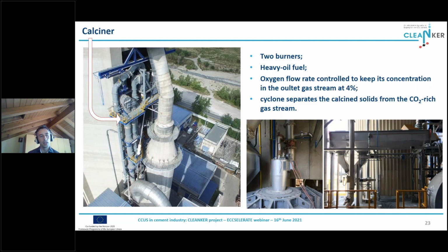So you can see the red one, the calciner, which is equipped with 2 different burners exploiting heavy oil as a fuel. We also have multiple oxygen injection for staging the combustion process and having a better control of the temperature profile along the whole calciner, especially in the hot region of the combustion region of the calciner, to avoid excessive particle sintering. On the right side, you have two pictures of the burner and of the screw conveyor, which is used to partially cool down the sorbent and to deliver it to the carbonator.